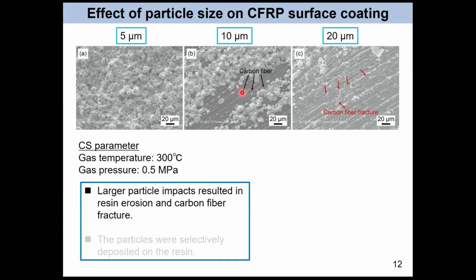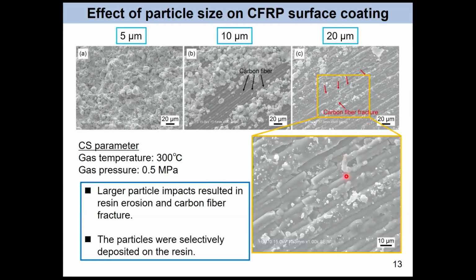And the naked carbon fiber we can see. So this figure shows that a 10 micron particle in this operating condition could result in the erosion of CFRP. And in the larger case, 20 micron particle size, this is a high magnification SEM; we can see carbon fiber fracture and also severe erosion occurs by the 20 micron particle impact. And interestingly, the small particle can deposit.